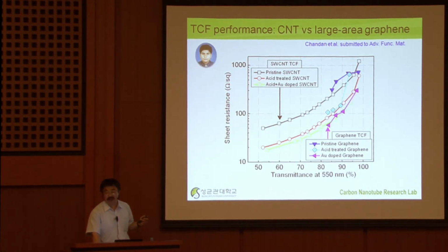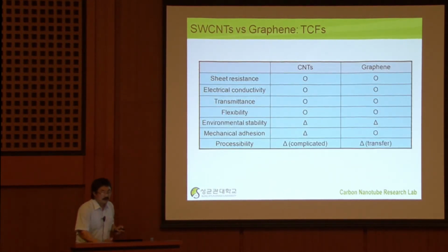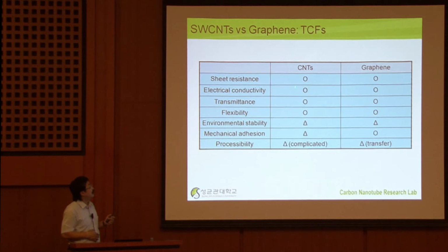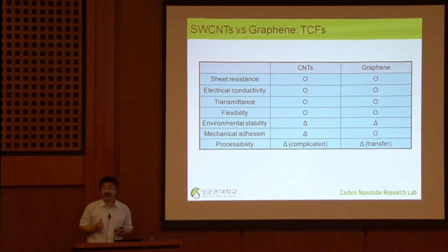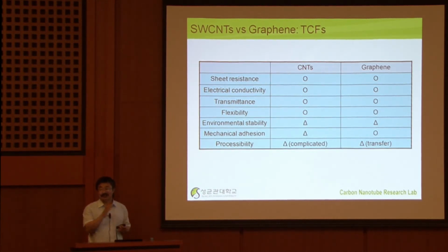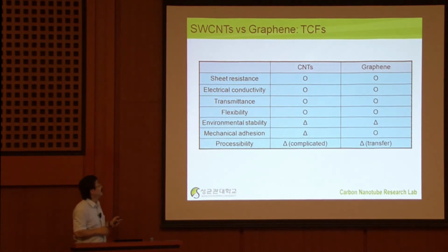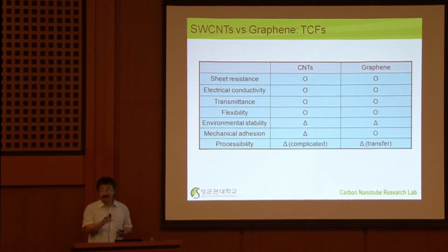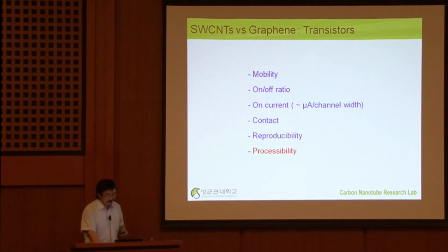Graphene can be also used for touch panel. So if you compare these two properties, almost the same. But of course, graphene has one serious drawback in terms of process, this transfer process. This is really a headache. If you work with graphene, transferring a large area graphene onto another substrate is really a headache. And of course, CNT, you have CNT powder, you have to dissolve in some solution and then make the film. This again involves quite a complicated process. So we have one thing good, one thing bad, but it's up to your choice.